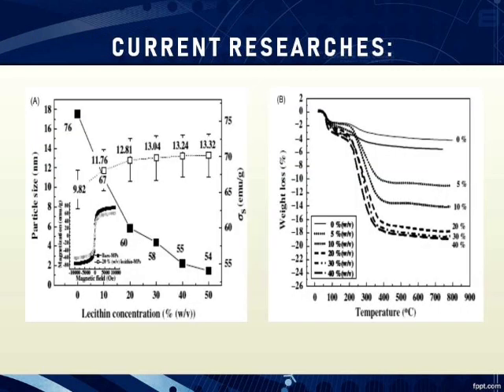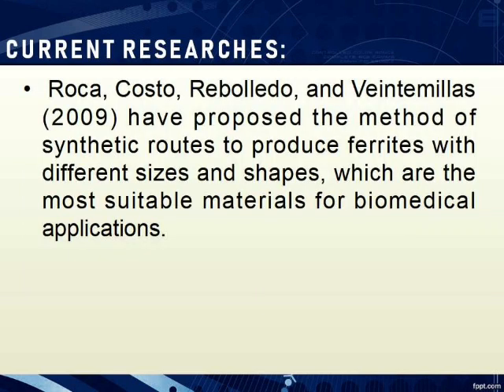As you can see, Figure A shows that as lecithin concentration increased from 0% to 50%, the saturation magnetization decreased from 76 to 54 nonlinearly. On the other hand, Figure B illustrates the percent weight loss with the increasing temperature for the absorbed magnetic nanoparticles with different lecithin concentrations.